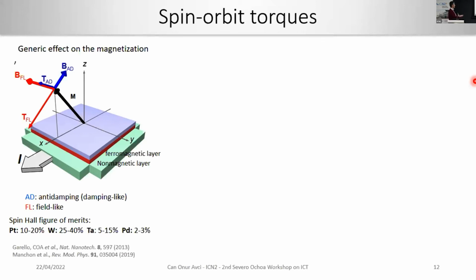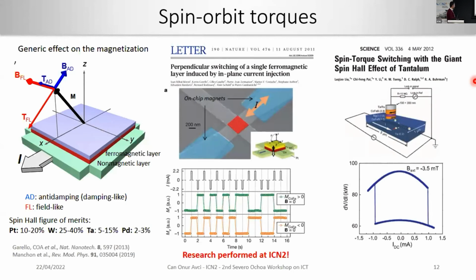And these torques can be measured because they also generate an effective field, called BDL and BFL here. For the materials, we measure the figure of merit of different materials, that is, how much spin current you can generate from a unit charge current. That is the fraction of spin current to the charge current that you inject into the system, and that's called the spin Hall angle if you consider just the spin Hall effect. In the case of platinum it is about 10–20%, and in the case of tungsten about 25–40%. You have also large effects in tantalum, but somewhat lower effects if you go to materials with lower spin orbit coupling, such as palladium.